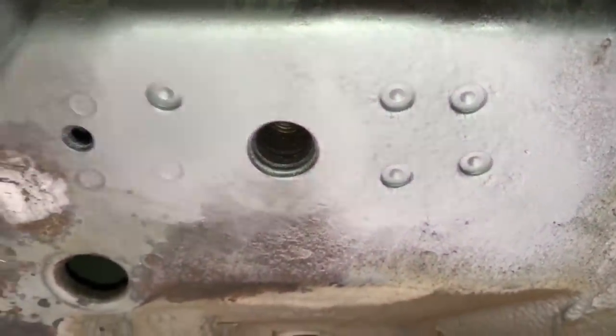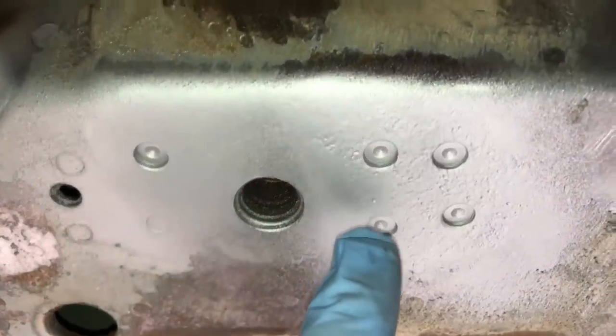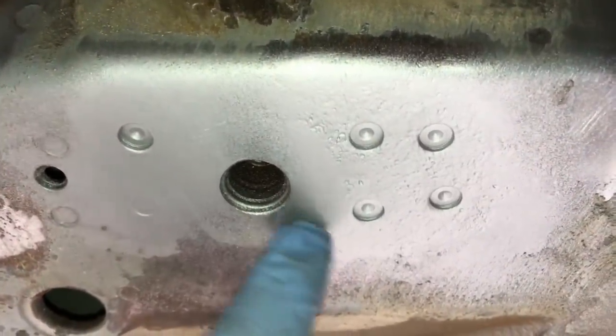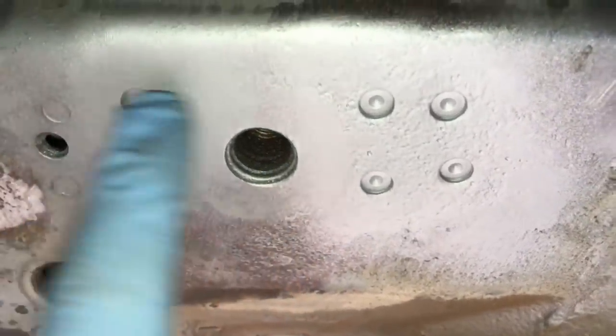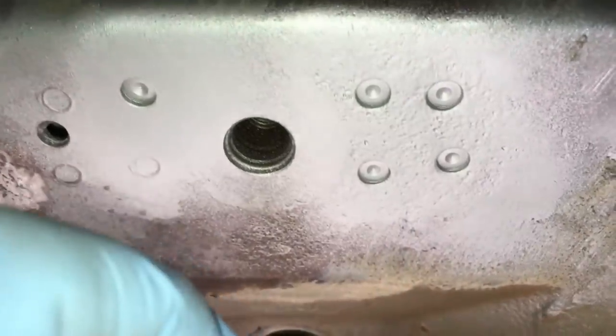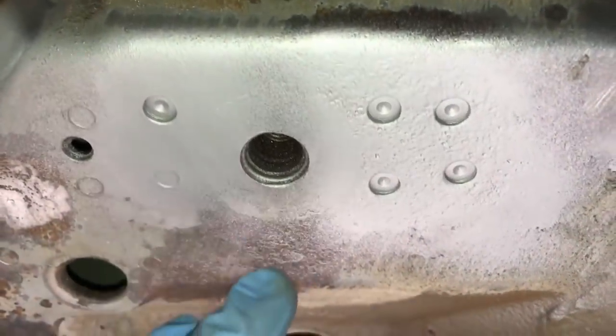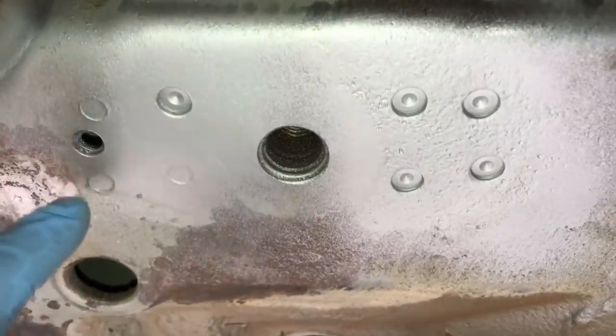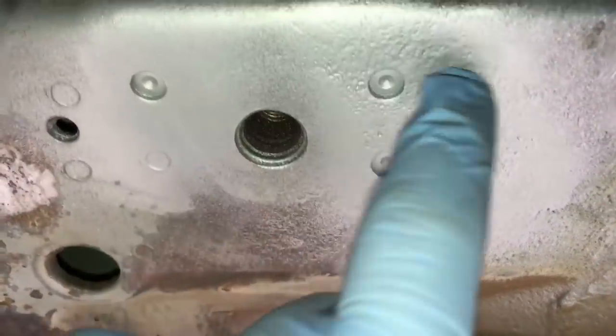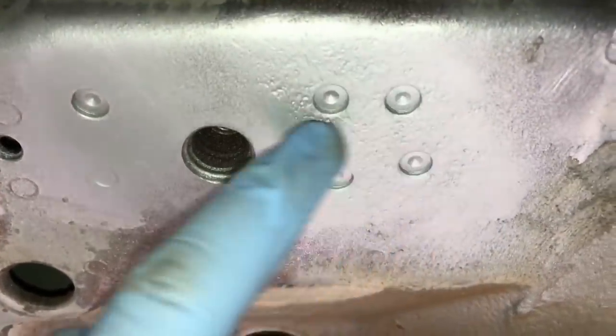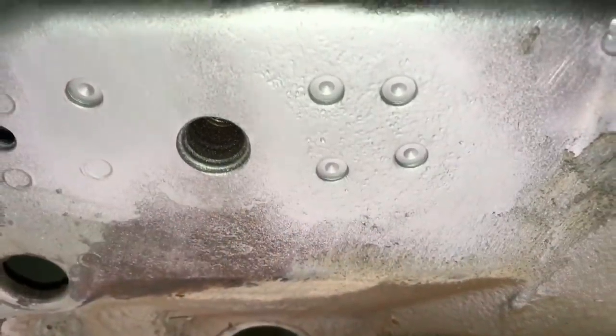And on the other side we've got similar things underneath. There's 8 spot welds that hold the lower part of the threaded platform to the rear axle carrier panel, and 5 of them were badly corroded enough to make me think they've been moving and could be cracked, whereas those 3 there look fine. So we're replacing these 5 with plug welds. This is weld through primer that's just gone on to the bare metal, and now we can start the plug weld process.